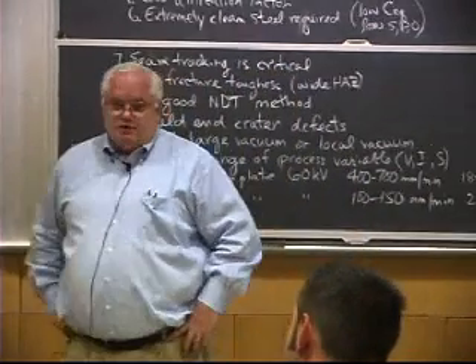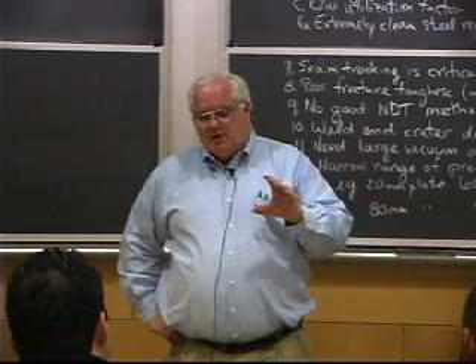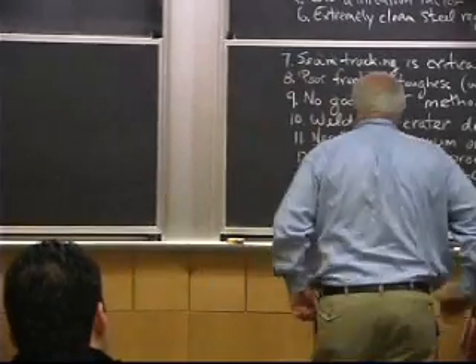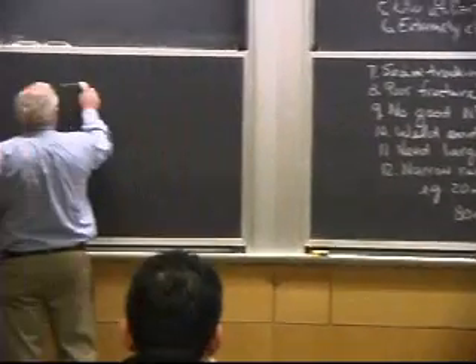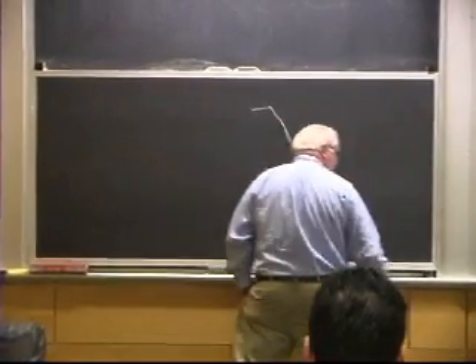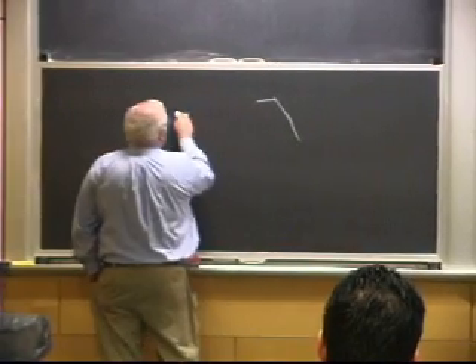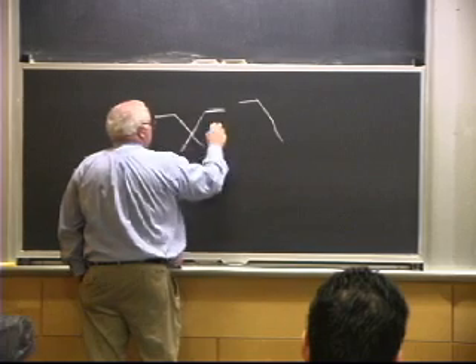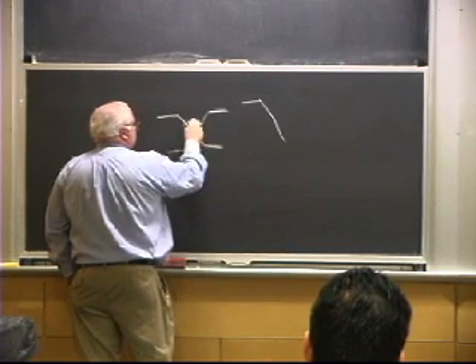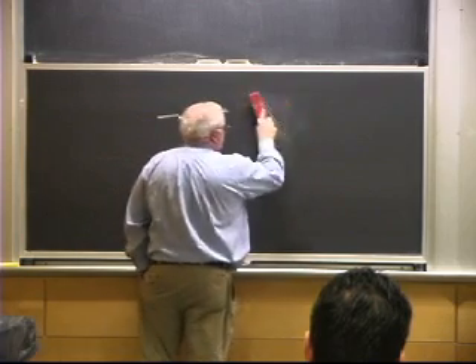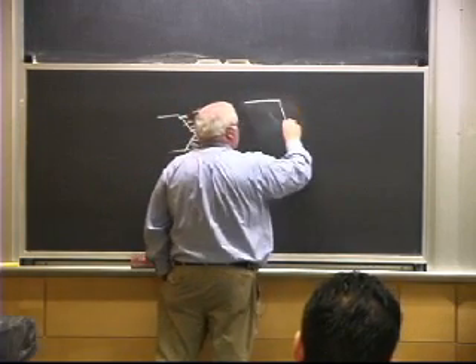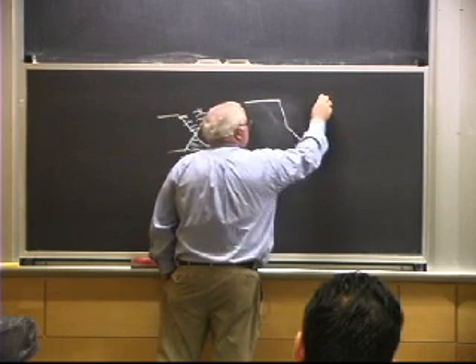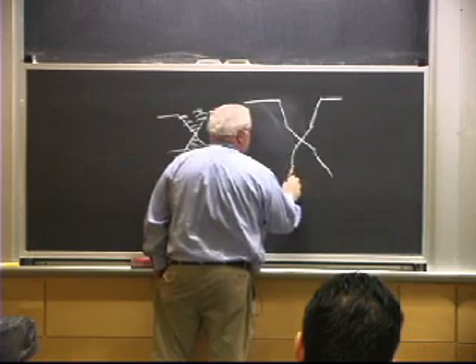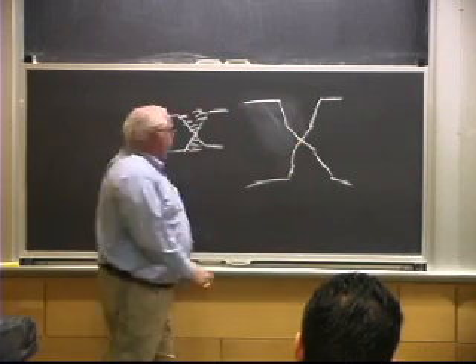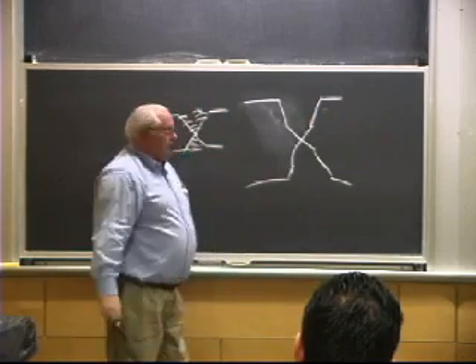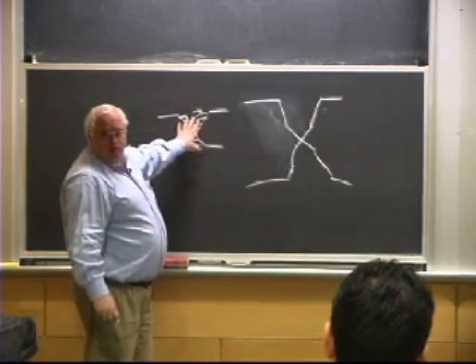It was done in battleships in World War II, but typically like a 2-inch plate, if you have some joint and you're doing stick welding. For thin joints, you basically just make your 2 plates like this and you just fill them up with different weld passes like this. For a very heavy plate, the X's get wider and wider at the top, and so typically what they'll do is something that might look like this, where they change the shape of the groove and have it narrower, so the thing doesn't get too wide at the top. Anything up to about 1 to 2 inches, you basically weld this way.